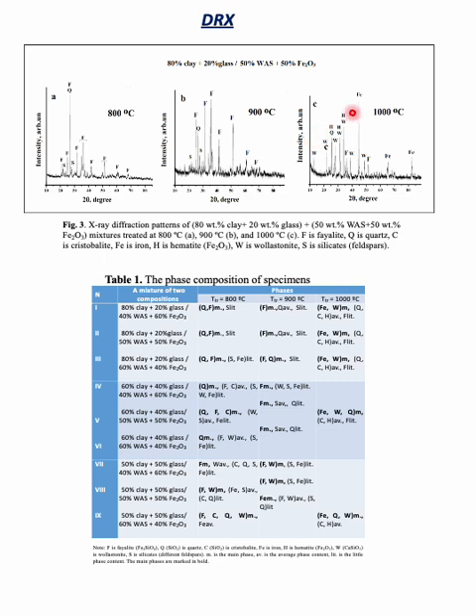Phases of hematite appear. In table 1, we can observe the composition of different mixtures. It is a mixture of two different components, for example, red clay plus glass with hematite, and also the principal phases in each temperature treatment. We can observe that the content of wollastonite increases when the glass content in the initial mixtures increases.